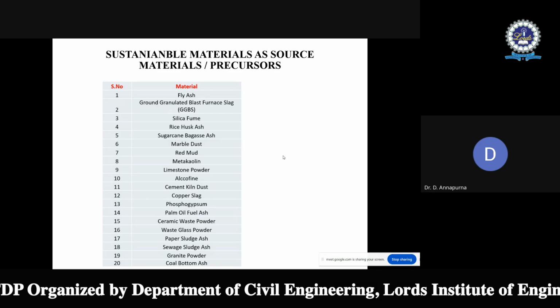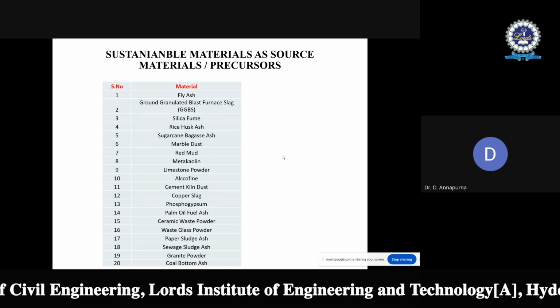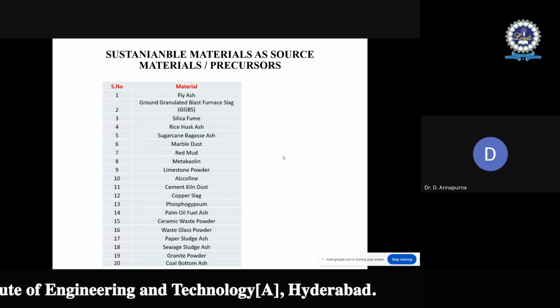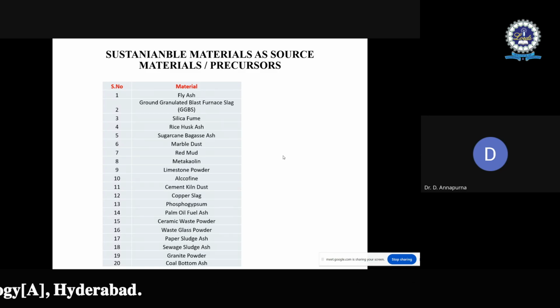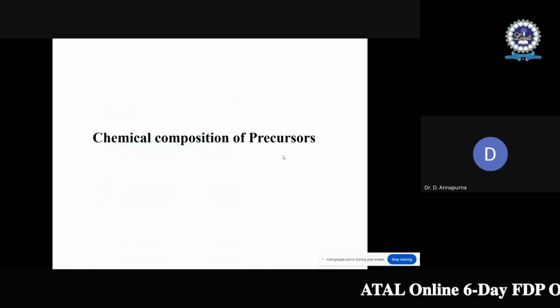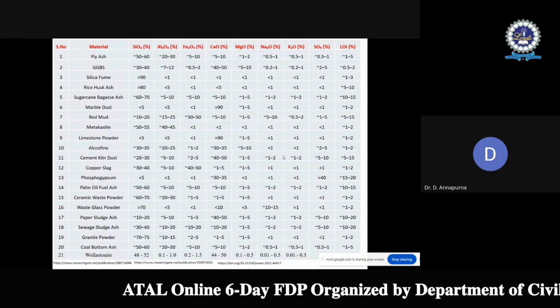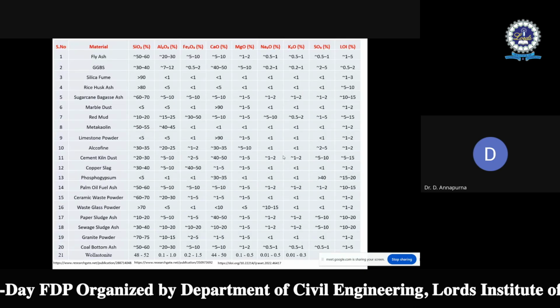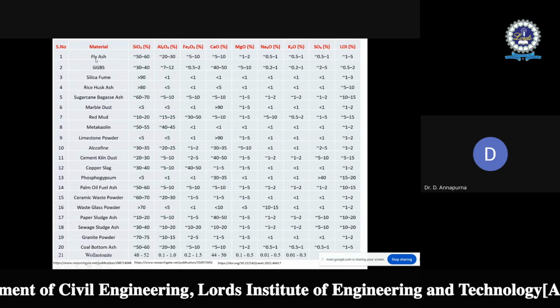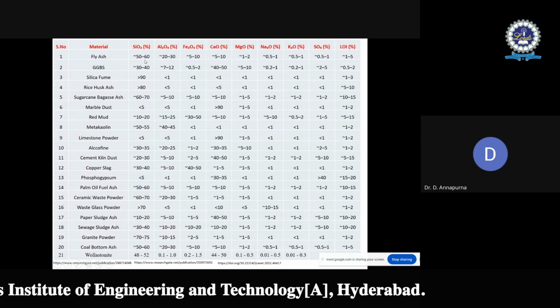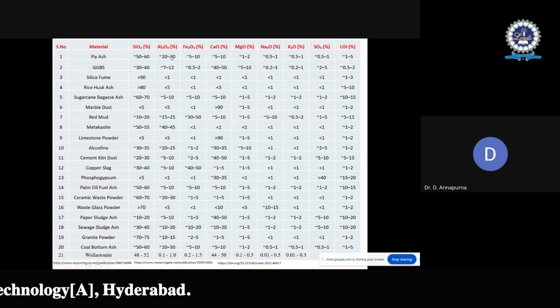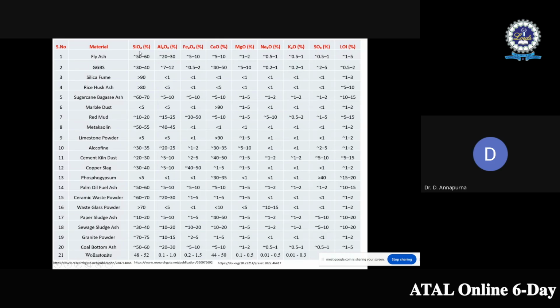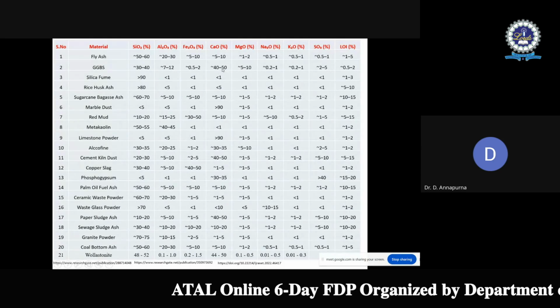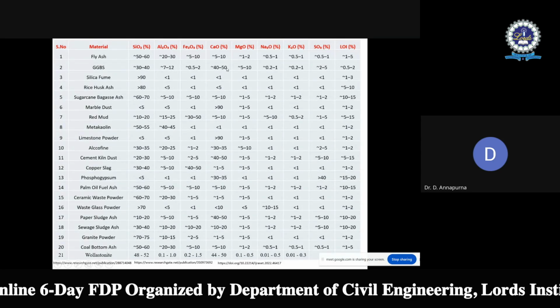Then how can we make use of these materials as precursors? Because to be called a precursor or source material, the material should be rich in silica and alumina. So let us check the chemical composition of each precursor. This is the chemical composition of all the materials, starting from fly ash. Fly ash has silica content of 50 to 60%, alumina will be 20 to 30%, then calcium will be 5 to 10%. Then GGBS is rich in calcium oxide, 40 to 50%, along with silica and alumina content.